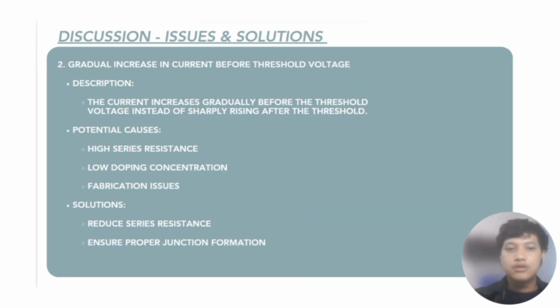The next issue is the gradual increase in the current before the threshold voltage. Basically, the current increases gradually before the threshold voltage instead of rising sharply after the threshold. The potential causes are high series resistance, low doping concentration, and fabrication issues during the lab. So the solution is we need to reduce the series resistance value and ensure proper junction formation.